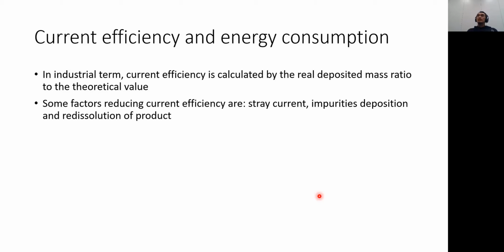Of course, current is only used for dissolving silver on the anode and depositing silver on the cathode. But there are many things that can use up this current, for example deposition of unwanted materials or dissolution of unwanted materials. For example, if the silver anode has copper or lead content, copper and lead can be dissolved in nitric acid. So a fraction of current can also be used to dissolve copper and lead into the electrolyte, and a fraction of current can also be used to deposit those impurities on the cathode. So if we want to have high current efficiency, of course, we need to limit this fraction of current that is used for any other things.